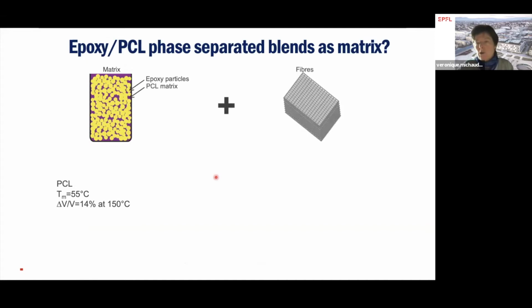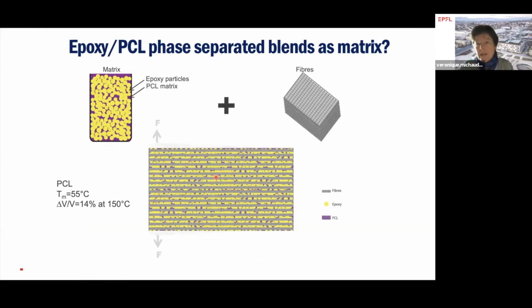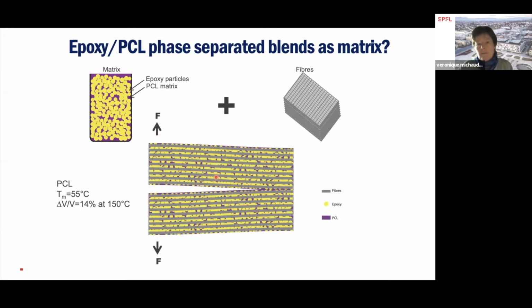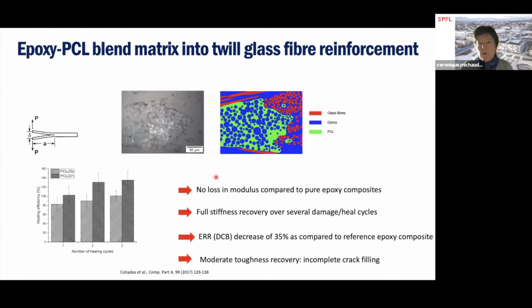So we put it into a composite with fibers. The idea again being that if you have a crack, then upon a small heating at 150 degrees for half an hour, for example, you have the PCL bleeding, and then you will end up closing the crack. So we saw that it actually works. We looked at the morphology, and of course, the presence of fibers will affect a bit the phase separation. With the big resin pockets having the normal phase-separated morphology, smaller resin pockets having a different morphology, yet we still see that it works.